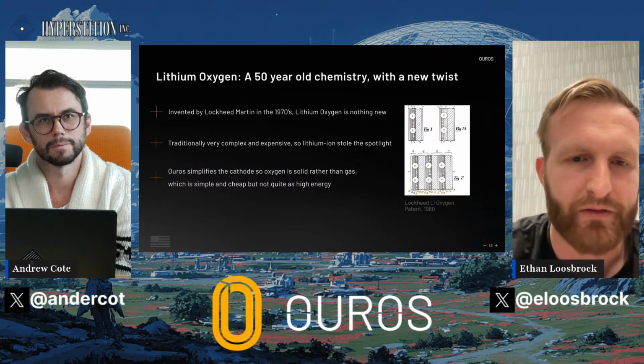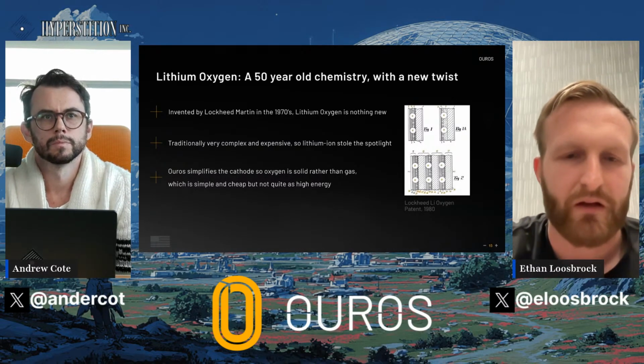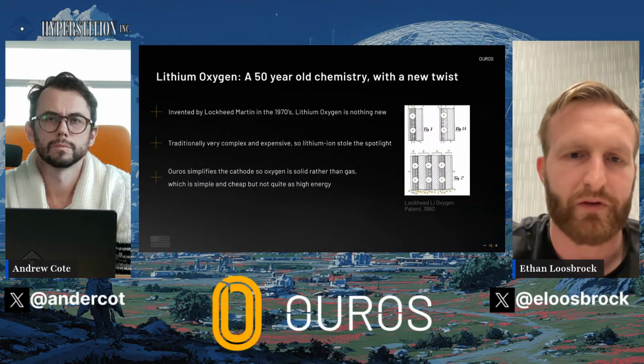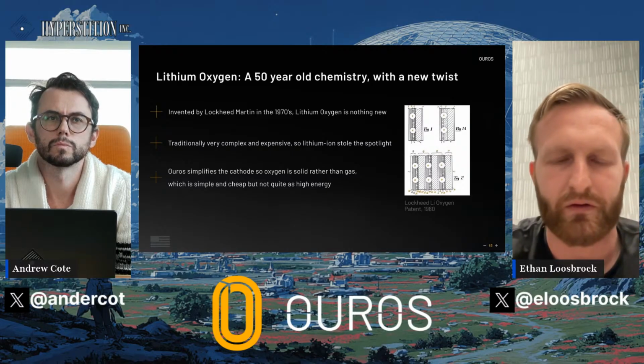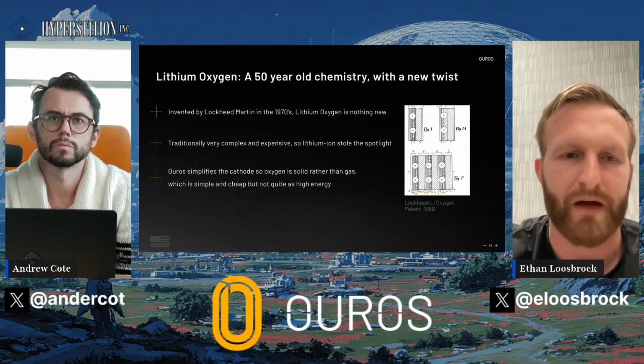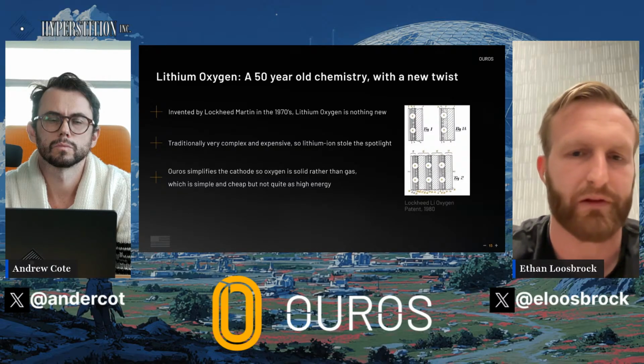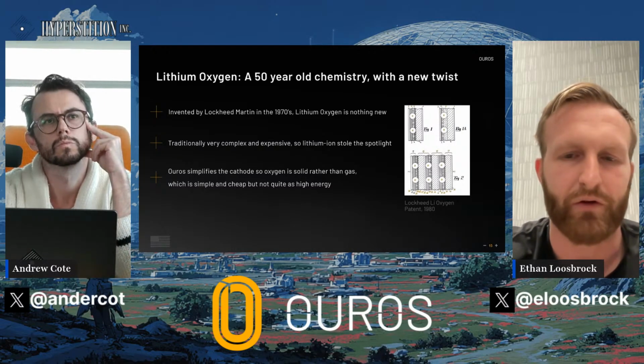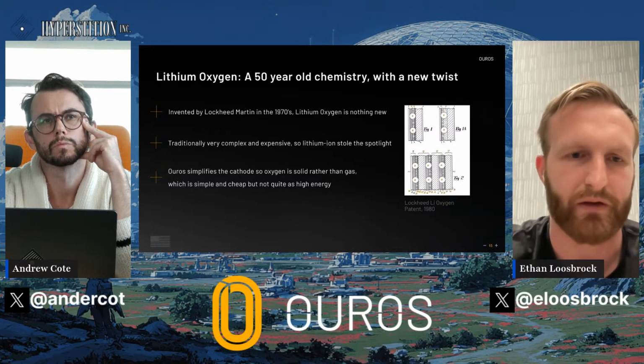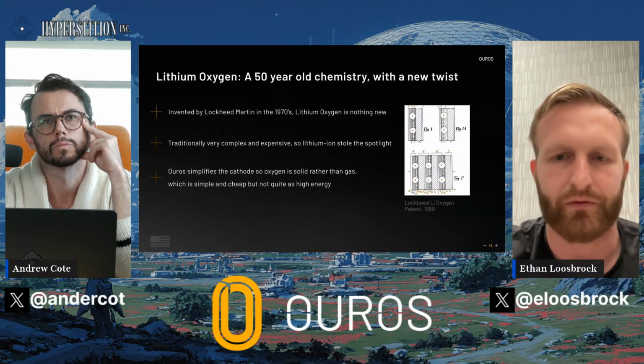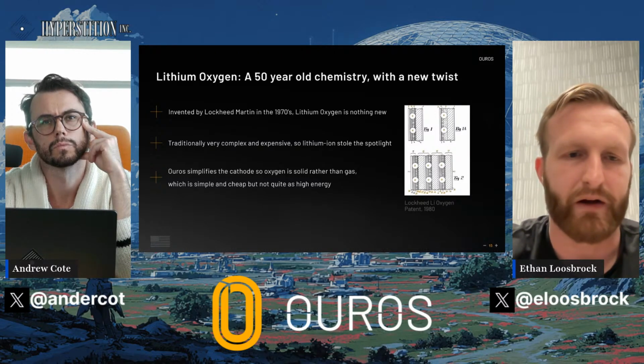So the history of lithium oxygen is that the first lithium oxygen battery was developed in the 70s by Lockheed Martin. Basically, you take oxygen from outside of the battery, and therefore don't have to carry the mass of it. Then you have a lithium metal anode, and you combine the lithium and the oxygen in this carbon structure on the cathode. It's incredibly complex. It's not really reversible, so you can use it once. In that way, it's almost like a fuel cell, but with very, very high energy density.